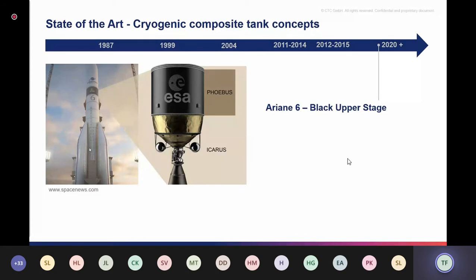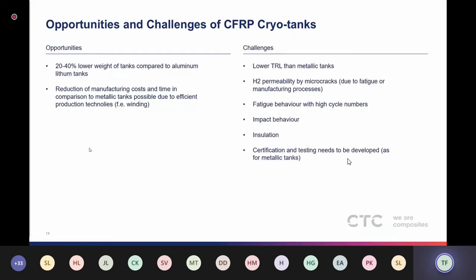To sum up this overview of the history of CFRP cryotanks, there are great opportunities. All these tanks show that the weight compared to an aluminum lithium tank can be reduced by 20 to 40%, which is of course a lot, and allows the weight savings in the tank area, which are required for longer range, or short and medium range hydrogen aircraft.